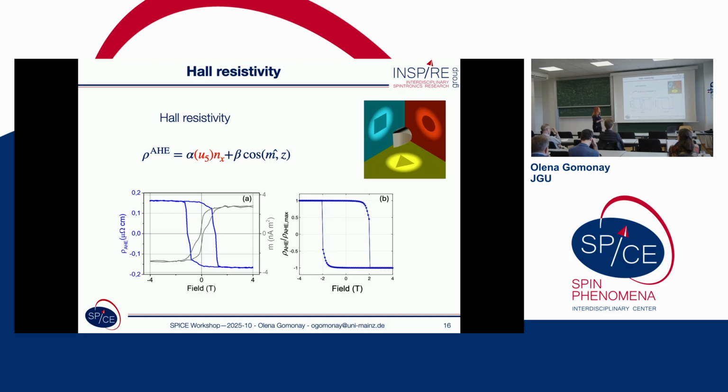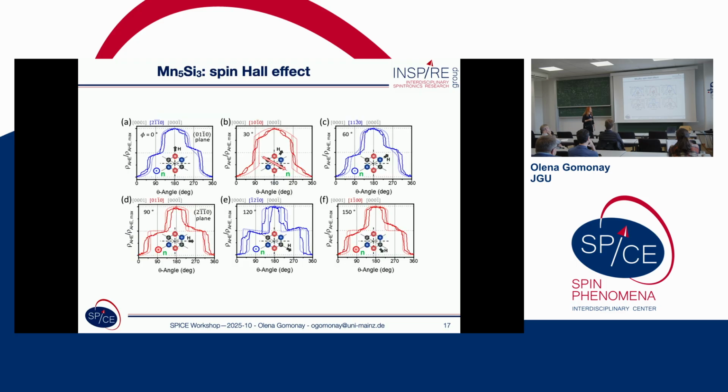So this is a theory, this is an experimental part, and they agree quite well. And the rest of the curves, which I will show, are taken somewhere here. So the value of the magnetic field is fixed at the saturation, but close to the coercive field, and then the magnetic field is rotated. And then when it's rotated, you can go to this area for certain projections, and go through different magnetic states.